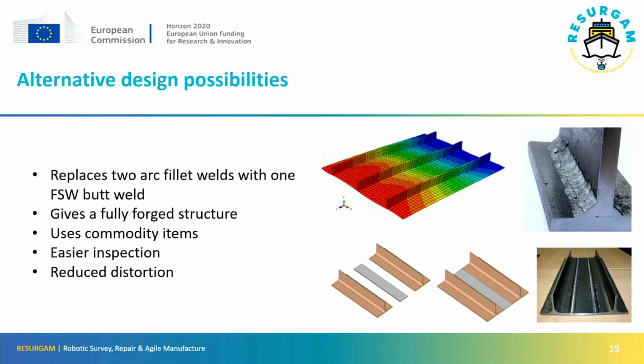So effectively what you're doing there is replacing what could be a defective fillet weld, and there we can see a fillet weld with defects. You're getting rid of that process and you're replacing 2 arc welds with 1 friction stir weld. So you're halving the number of welds you make, and these are forged welds rather than cast welds. So potentially you're ending up with a fully forged structure, much less deformation, and potentially stronger. And we've talked to classification societies such as Lloyd's, and they say there's no reason why this can't be done.